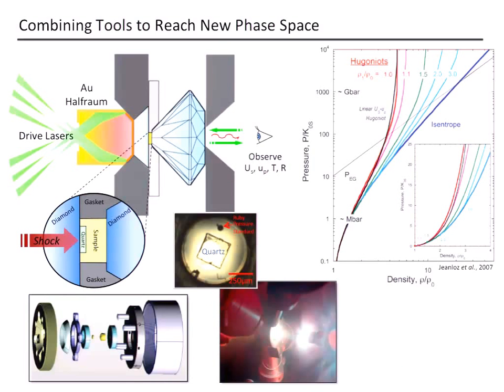So this was really a collaboration between the group at Berkeley where I did my thesis and the group at CEA where I did my postdoc. What we do is we pre-compress a sample of either hydrogen or helium or mixtures in a modified diamond anvil cell where the back diamond is actually a thin plate rather than a brilliant cut diamond like this.